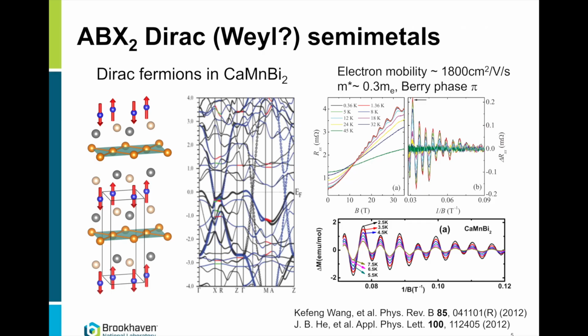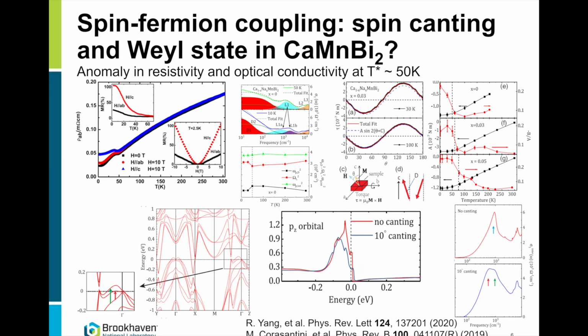DFT calculations do show you the Dirac cones here. And then, this is a busy slide, but I'll walk you through. So this is a resistivity measurement as a function of temperature. Here the resistivity shows some kink at around 50 Kelvin. You see something, you want to see a Weyl point or Weyl system. You say, yeah, of course, that's what it is, Weyl.